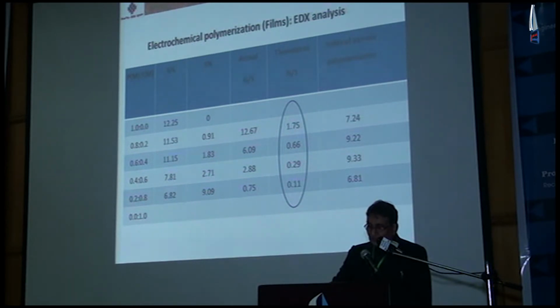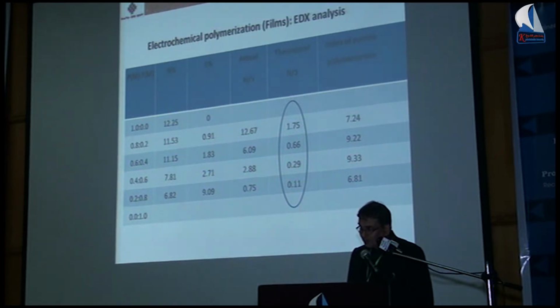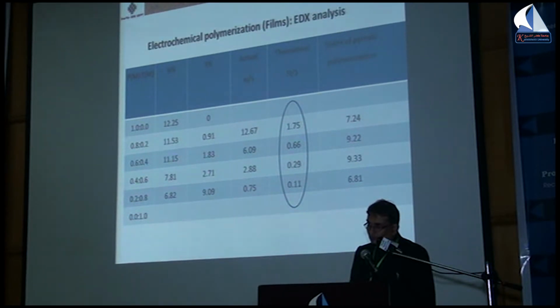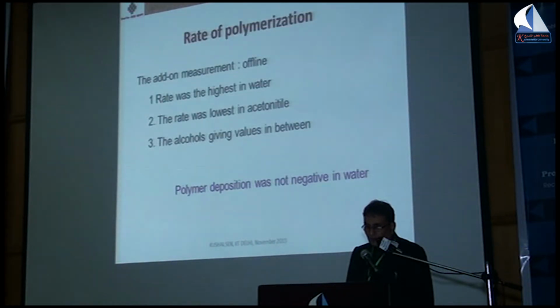So one found that theoretically, obviously, the ratio was changing from one higher value to a lower value. But when you do the actual measurement, the values were higher. The nitrogen was higher, which means that pyrrole, despite being low, is going more onto the surface, getting more polymerized. And therefore, one could find that despite the fact that the content of pyrrole is less, after the polymerization the pyrrole polymer was more.